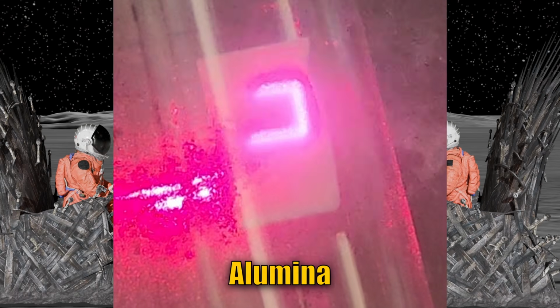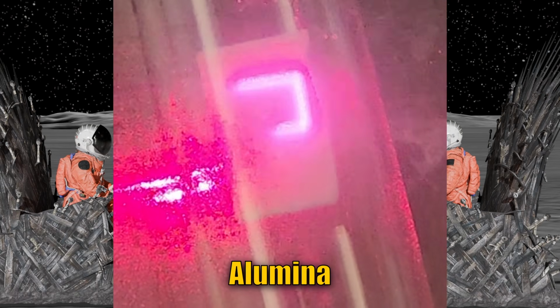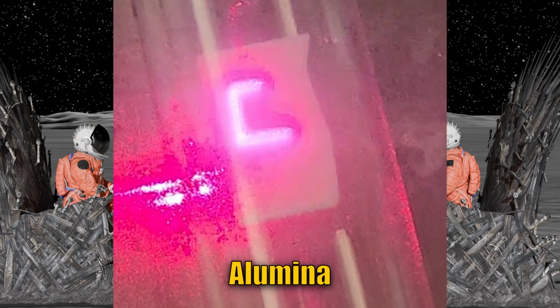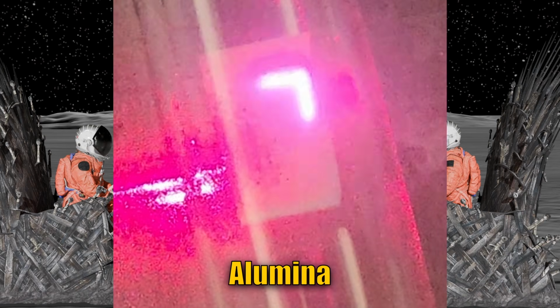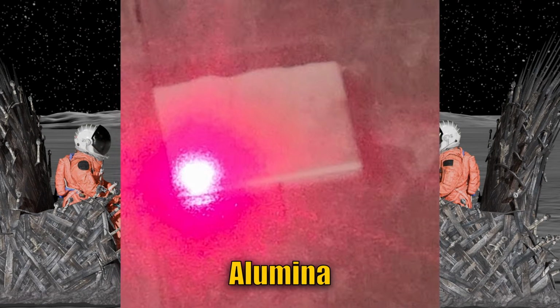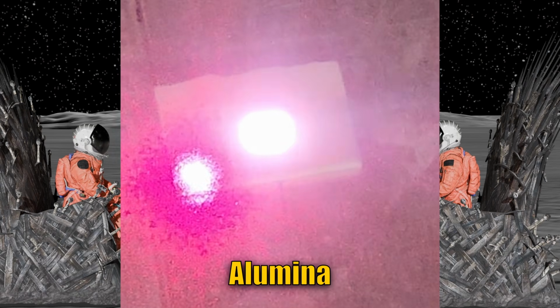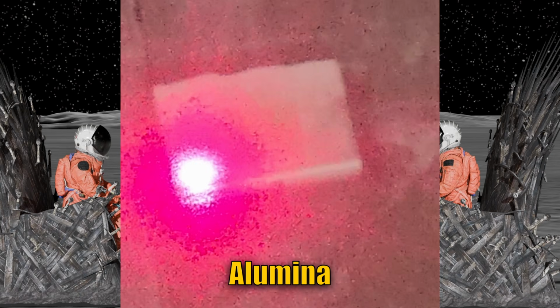Alumina was pretty difficult. I'm still working on that one. It has its inherent problems because of its reflectivity and its extremely high temperature and reactivity. But the other metals, absolutely. Magnesium, actually incredibly easy. Iron, incredibly easy. Titanium, a little bit more difficult due to its color, but absolutely was able to reduce that, as well as calcium. And then you mentioned the electrical conductivity.